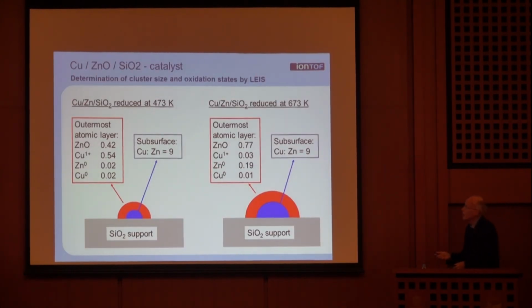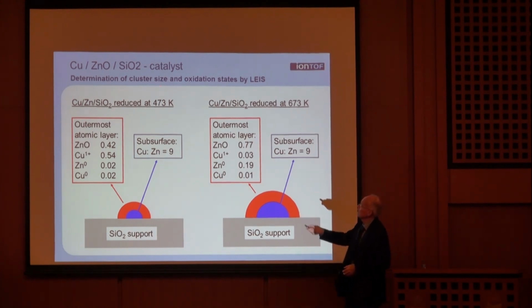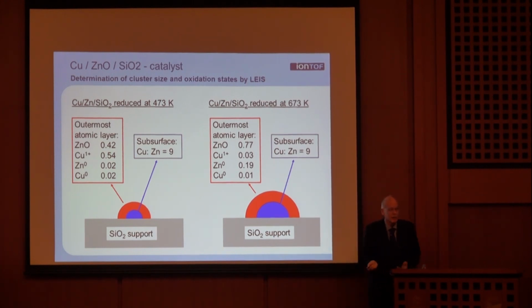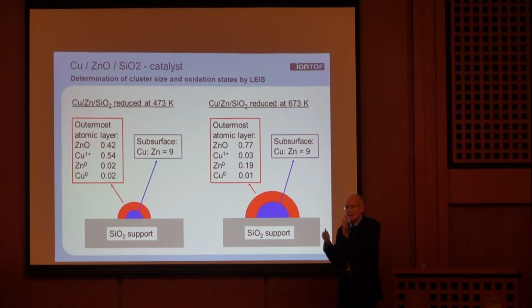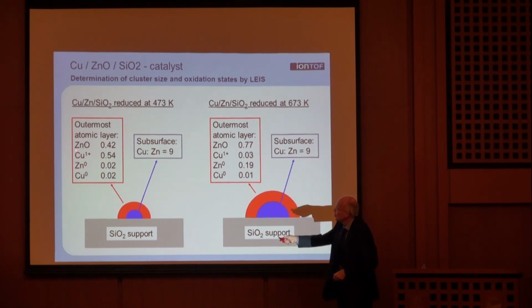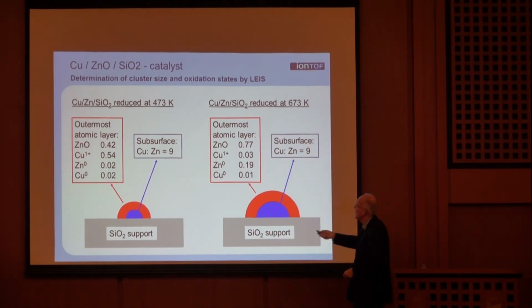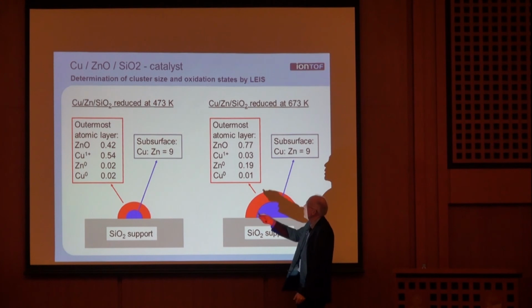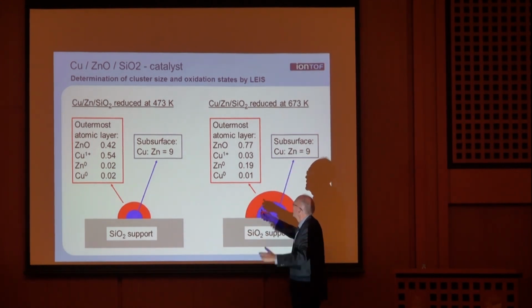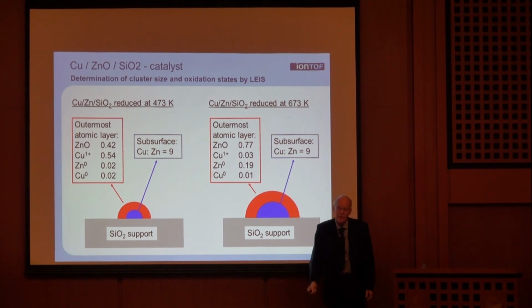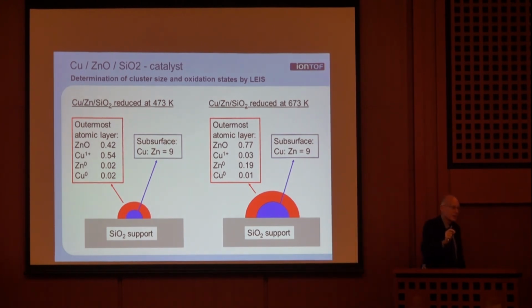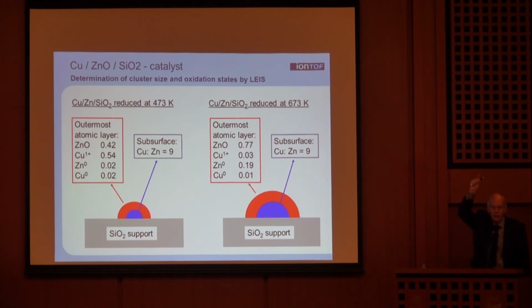And this is an example where we did that on a real catalyst, and there's the Topsoe company that is very famous for this kind of catalyst. They helped me to get the right chemistry to prepare the catalyst. And you see here, I show you the oxidation states of copper and zinc for two different temperatures. And of course, when you go to higher temperatures, it sinters, the clusters get bigger, and you get a different oxidation state. So you get the oxidation states of these elements, element specific for the outermost atomic layer. And that's fun.